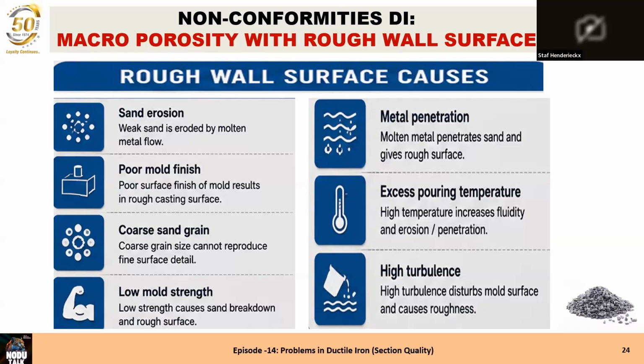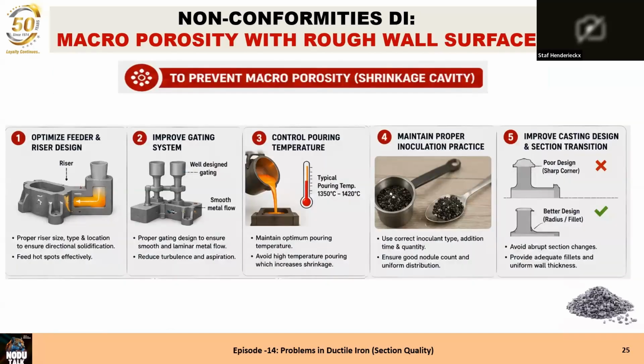Metal penetration we can have if the mold is not rammed properly, then the metal can easily penetrate, and if there is no good coating on it, it will penetrate. The excess of pouring temperature will also give a rough surface, and a high turbulence of pouring will also give a rough surface. So this is a rough wall surface. It's not really porous. To prevent the macroporosity, of course, on the left in picture 1, we can see the riser. The riser is the main solution for macroporosity.